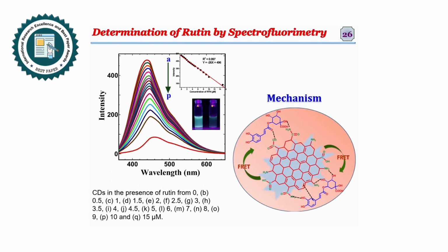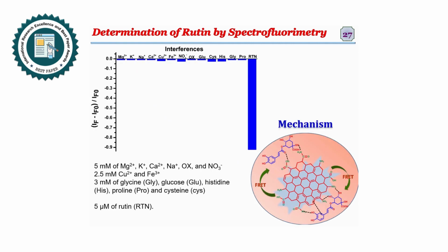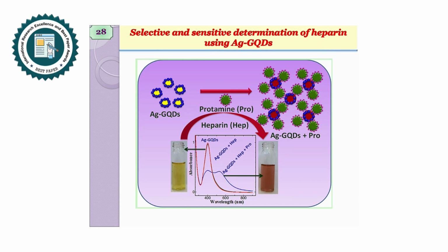So the determination of rutin by the spectrofluorimetric technique: as we already saw, the carbon dots have an intensity around 400, and after adding rutin, the emission intensity is slightly quenched with each addition of 0.5 micromolar of rutin. After 15 micromolar of addition of rutin, the emission intensity is drastically quenched. This is due to a fluorescence resonance energy transfer mechanism, and these carbon dots are highly specific to the determination of rutin among possible interferences such as Mg2+, potassium, sodium ion, calcium, copper ion, and some amino acids and everything.